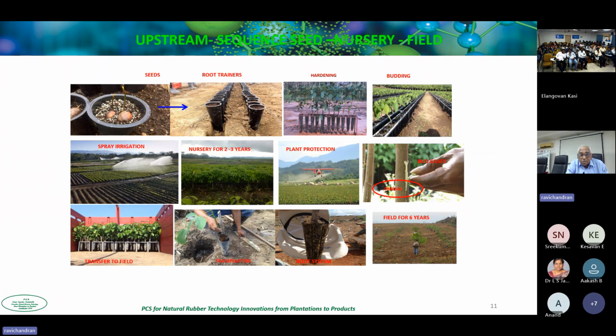So again, this is a sequence: seed to root trainer, to hardening of the plant, to budding, then to bud grafting. Then in the nursery, we do plant protection. The nursery for 2 to 3 years where it grows, we need to spray irrigate. Then we transfer to the field and put it in the field for 6 years. In between the 6 years, there's no yield from the tree. But what we do is you grow corn or you grow pineapples or you try and do some supplemental income during that period.